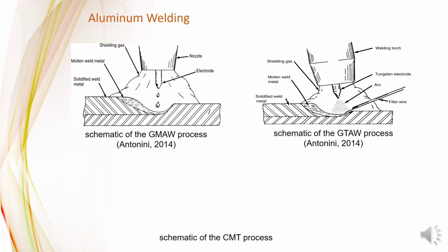CMT, cold metal transfer. CMT is a modification of the MIG welding process, has a low heat input process, and uses the mechanical droplet cut methods. CMT welding works by joining material with a high deposition drop transfer method and low heat input, resulting in a very low spatter. CMT welding advantage is that it can increase welding efficiency, flexibility, welding speed, and tensile strength.